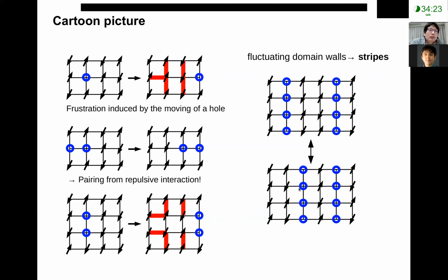As I said, we consider a doped hole in an antiferromagnetic background. If we move the hole, it would introduce some high energy spin. However, if we have two holes together, and we move these two holes to the right, we find that the antiferromagnetic background is recovered again. So in this way, the system would be happy.